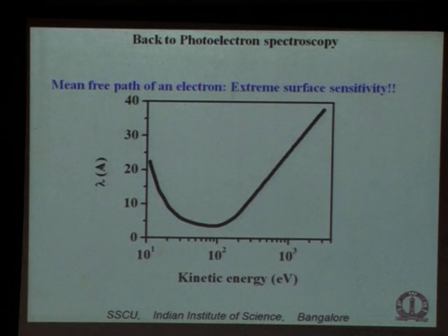So this inelastic scattering is mostly from phonons, is it? No, electron-electron interactions also contribute quite a bit. So other electrons which are also ejected? Yes, and electron energy loss processes take place, not necessarily always of the ionization kind, but internal excitations take place. In the low energy, you're dominated by more interaction with the lattice. Right.